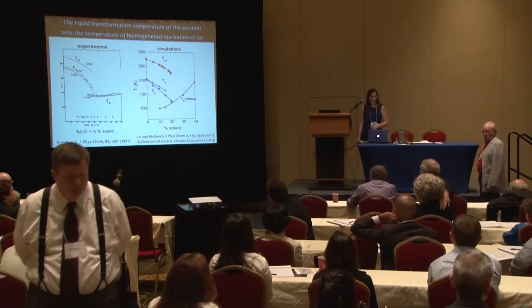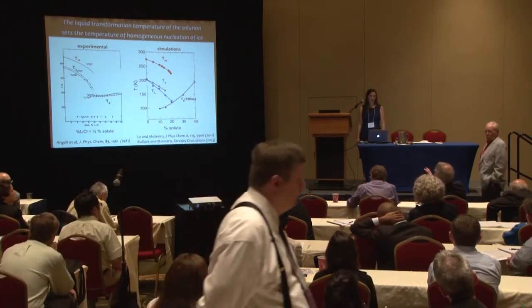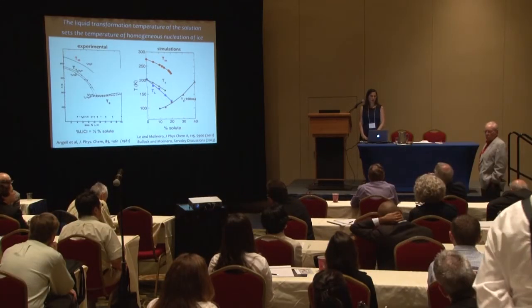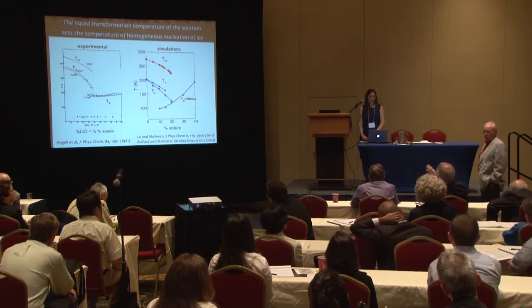Question: Do your models predict the volumes produced in these various configurations? Answer: The density of liquid water is right in the model. The density of ice is lower than the experimental one because there are no hydrogen bonds to straighten — in experiments, liquid water has many bent hydrogen bonds that straighten in ice, giving a density difference of 0.917 vs 0.997; in the model it's only about 3% vs the experimental 7%.